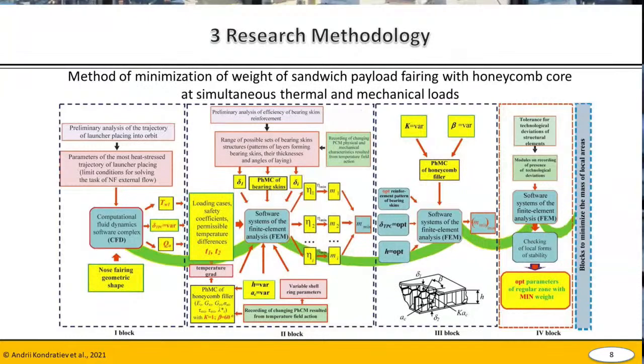Slide 8 shows the approach to the weight optimization of the composite sandwich payload fairing under thermal and mechanical loading. The procedure is divided into 4 blocks. The first block incorporates the preliminary analysis of flight conditions to get necessary boundary conditions in form of heat fluxes and temperatures. Also, here we provide the analysis of the thermal protection coating.